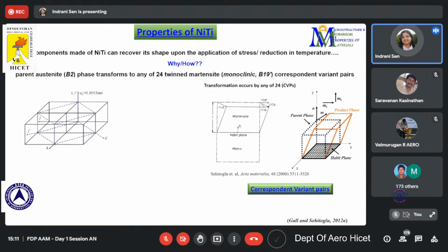If we have different grains, like in polycrystalline materials, this transformation can happen through different CVPs for different grains. That is also possible. But whatever it is, one set of transformation from one austenite single crystal to another martensite single crystal can happen along one out of 24 different CVPs. And in whichever way it is happening, there is a habit plane, which is a common plane between the austenite and the martensite. The checkered plane here is the habit plane.